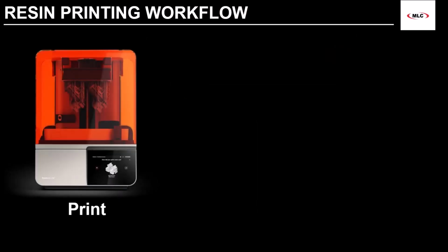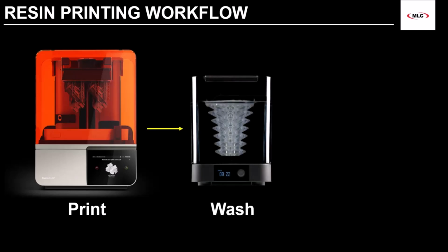That's because we're dealing with a liquid-based printing system. Once a resin part finishes printing, it has all this liquid resin coating it that we need to deal with before handling with our bare hands. This is where the wash comes in. After printing, we submerge the part in the wash, which agitates a solvent bath, the solvent typically being isopropyl alcohol. Washing takes no more than 20 minutes and is followed by at least 30 minutes of air drying. At this point, our part is free of any uncured resin and is now safe to handle.